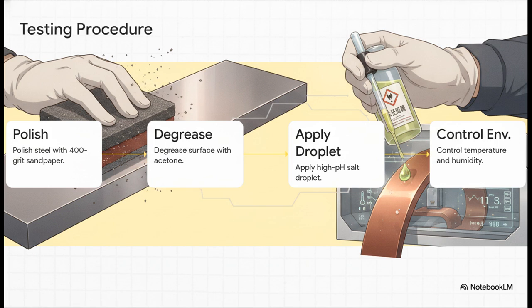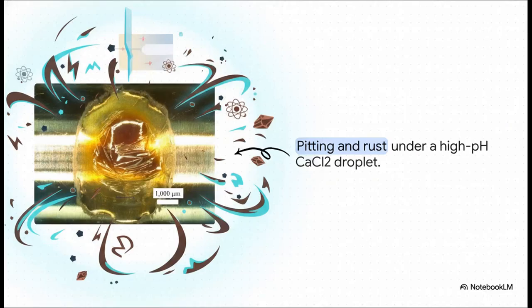And finally, the researchers tightly control the temperature and humidity. The whole goal here is to create an evaporative condition where that salt deposit maintains a saturated liquid right on the steel surface. It's a perfect storm. And the outcome is incredible to look at under a microscope. Take a calcium chloride droplet on that 316LN stainless steel, for example.